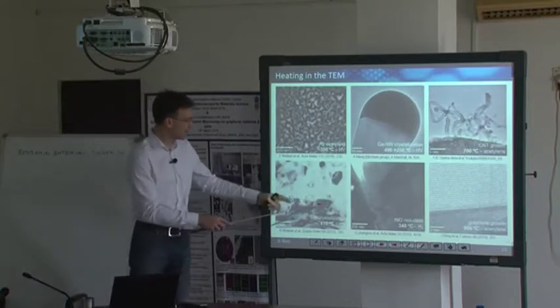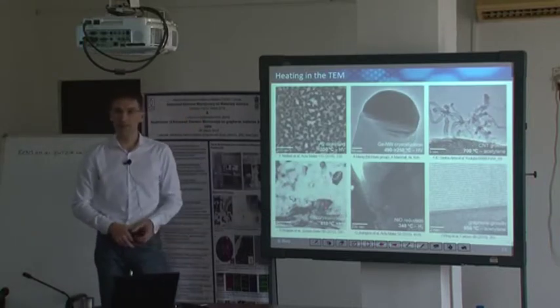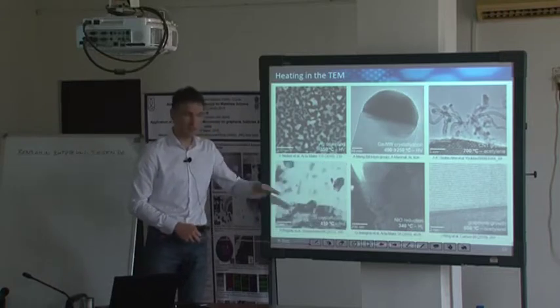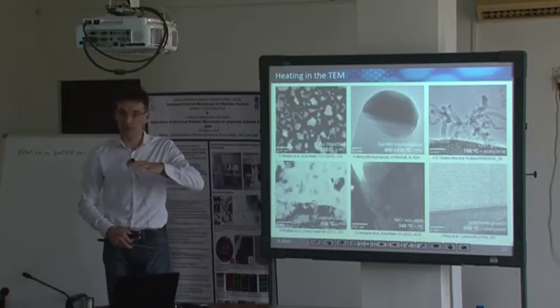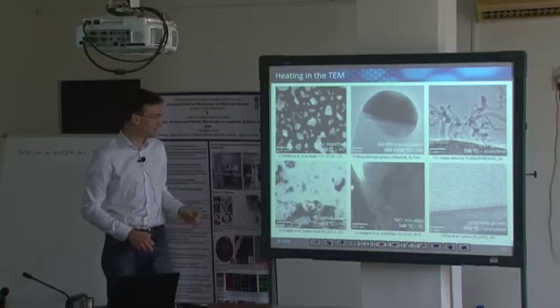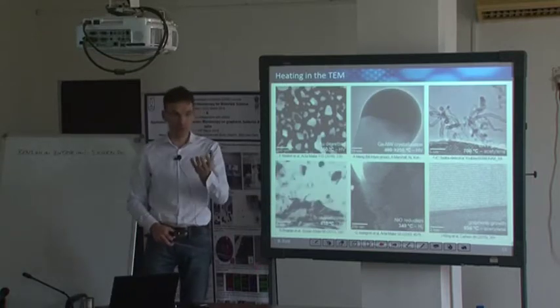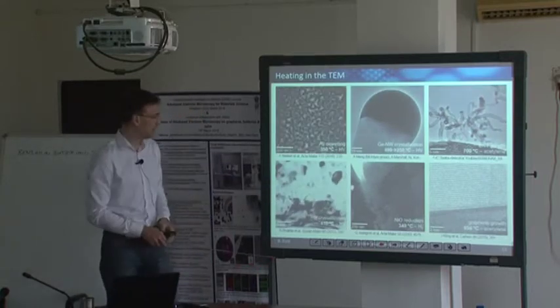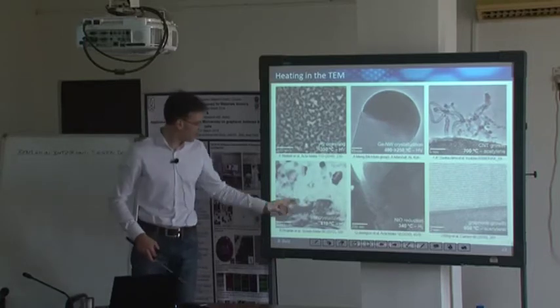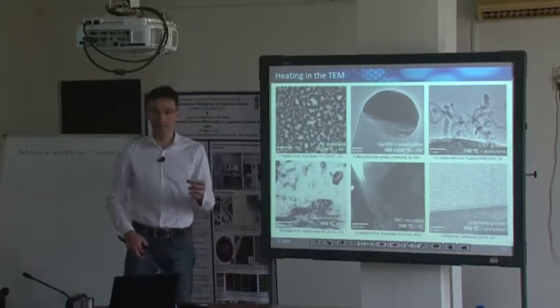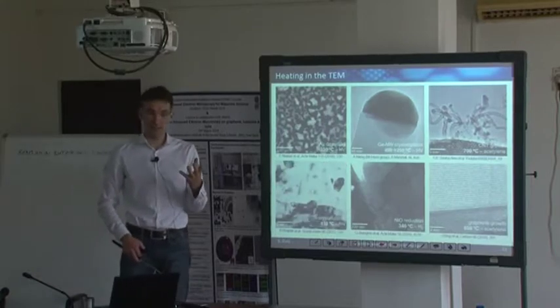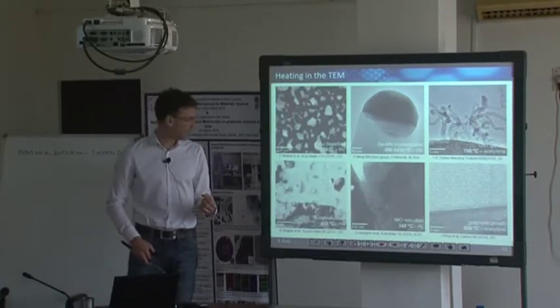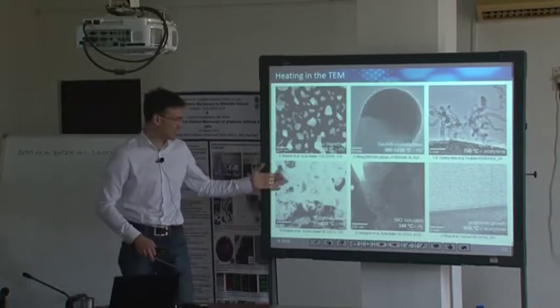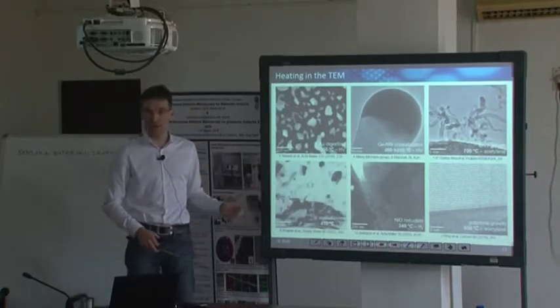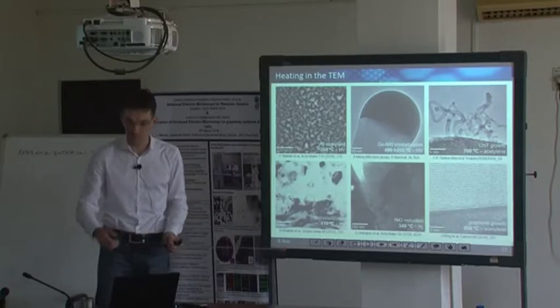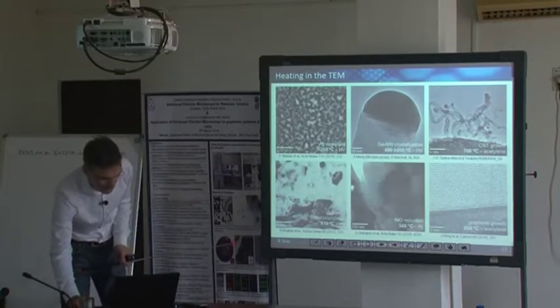silicon layer. In this particular case, the question came up how the aluminum from this lower layer is transported into the upper layer through this diffusion barrier that was deposited as well. And it turned out that in some areas, which you hardly see here, this diffusion barrier layer just breaks, and you have a very rapid push-up of the silicon because there is some stress involved. Stress occurs, and that just causes the failure of this interlayer.